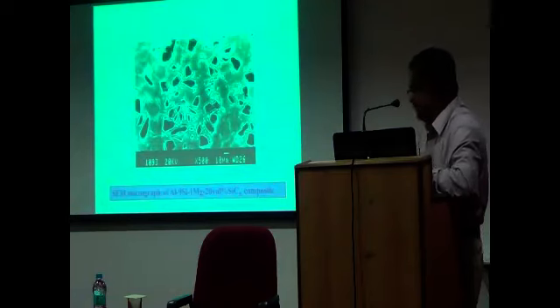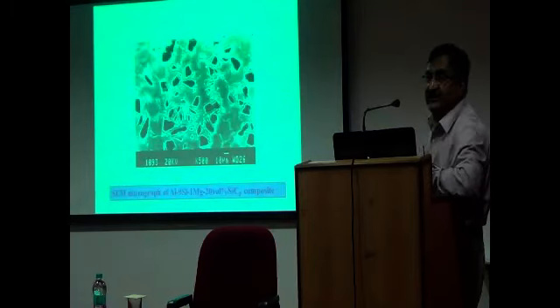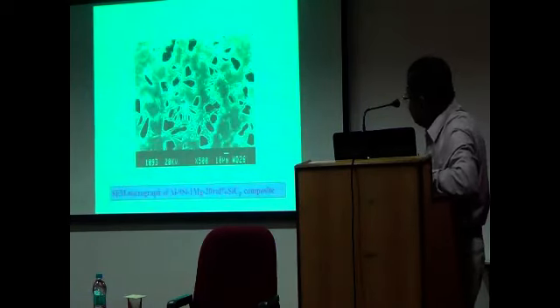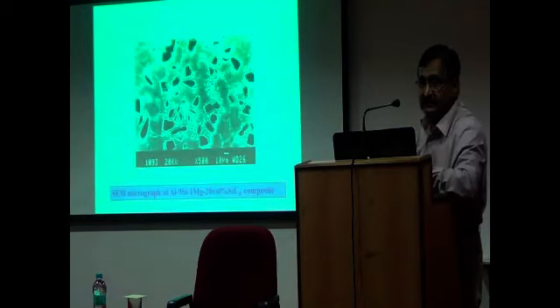This is the material that we produced in our laboratory. Whatever you see as the continuous matrix is aluminum. These dark particles are the silicon carbide particles. You can see they are about 20 to 30 micron size particles. When we have these particles embedded in a continuous matrix, this becomes a composite. This is produced in the simplest way in our laboratory by what we call the casting process.